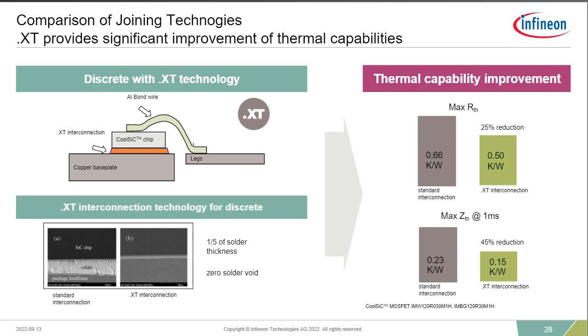So your standard TO247 devices in the market use a soft solder connection here. It's a rather thick connection layer, as you can see here on the left. And this creates a mismatch in terms of the thermal coefficients of expansion of the devices and can lead to delamination if you had a high delta T application environment. But by using .XT technology, we're actually using some type of sintering process, which creates a molecular bond between your chip material and your substrate or your lead frame material. And the thickness here is 1/5 the thickness you typically see in that soft solder assembly.